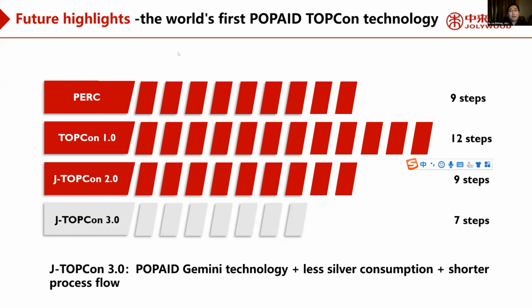Okay, in the last month we announced our POPAID technology. We announced the second generation J-TOPCon technology, POPAID TOPCon technology. Before that, Jolywood's first generation TOPCon technology was based on LPCVD and ion implantation, and the process has about 12 steps, so the cost is much higher than PERC. Now we developed a new equipment we named POPAID. This equipment can reduce the process steps from 12 to 9 steps. It's almost the same as PERC, and the cost will go down rapidly.